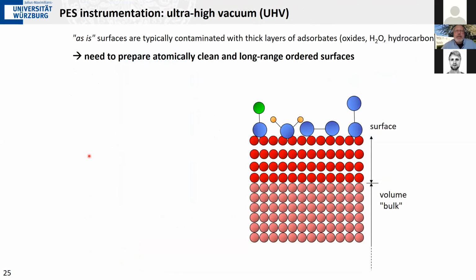But I wanted to argue why we need a vacuum. And the point is the following. If you have a material with the surface, and that's shown here, you have a bulk, a volume, that defines the crystalline properties of your material. At the surface, the atoms may be a little bit relaxed or show some surface reconstructions. And then typically, if you take a material at ambient conditions, ambient atmosphere, it will be covered with adsorbents. There will be water on your surface. It may be oxidized. You may have some CO2 molecules sitting on there. Somebody may have touched on the surface, and you may have some organic compounds out there. And so typically you have a situation like this.